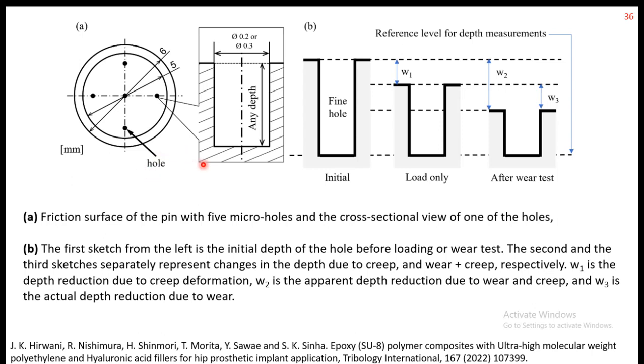So one of the problems with this kind of biotribological test is that these polymers soak a lot of fluid, basically water and other proteins, and because of this the wear evaluation becomes a very big problem. Here, what we did was make some holes on the pin surface, and as the pin wears out, the depth of the hole reduces. This is how we find out the overall wear. We made 5 holes at different places and measured the depth of these holes to evaluate the wear.